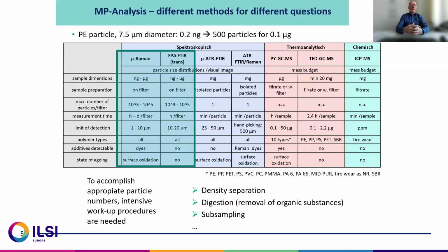If we go a little bit more into detail with the particle-based method, shown here for Raman, for example, the problem is always the detection limit. If we have, for example, a polyethylene particle with a diameter of 7.5 micrometers, the mass of this particle is only 0.2 nanograms. That means to reach the detection limit for a mass-based method, you need 500 particles to reach this limit of 0.1 micrograms. However, the disadvantage of the spectroscopic methods is that to accomplish appropriate particle numbers, you need an intensive workup procedure like density separation, digestion, subsampling, and so on. I come to this later.